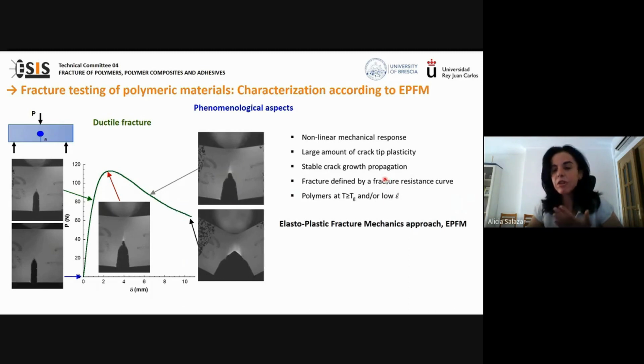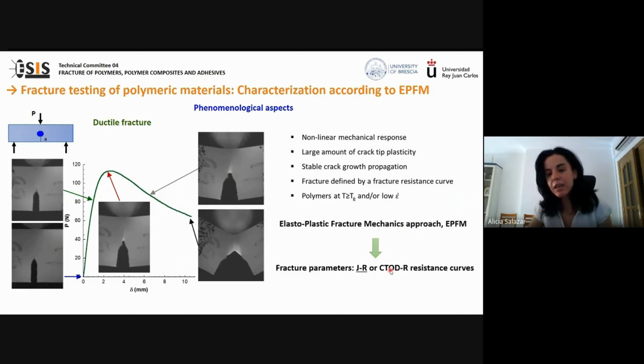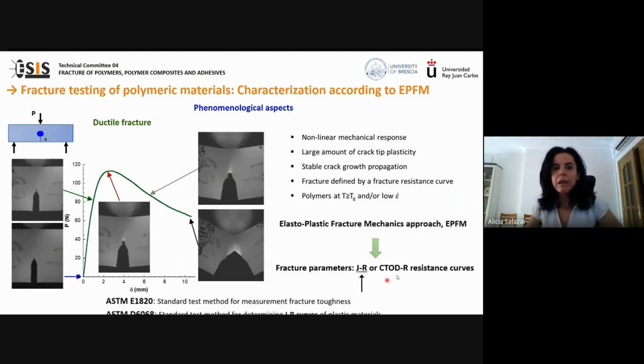Finally, this type of fracture occurs in tough polymers or, in general, at temperatures higher than the glass transition temperature and a low strain rate. The fracture parameters are the J integral and the crack tip opening displacement, or CTOD. And taking into account the stable crack growth, the fracture parameters are the JR curve or the CTODR curve. In this course, only the determination of the JR curves of polymers is described, and the standards are the ASTM D6068 and the ASTM E1820.